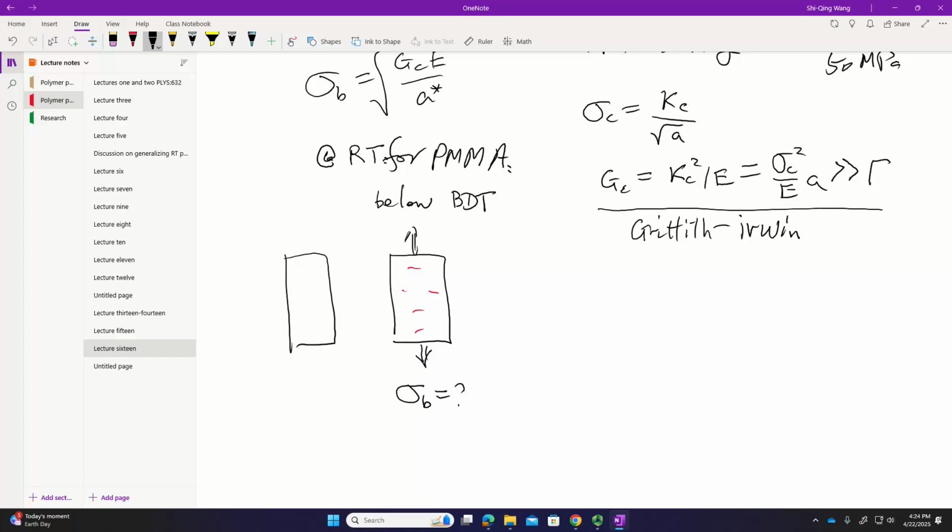understanding, gee, what is this nominal strength? The way I determine what this nominal strength is, is I do another experiment. Instead of counting on this unknown distribution of flaws, why not make a big cut here with known size? From that, I could operationally determine at the onset of fracture what happened, and it turns out to be given by this, according to